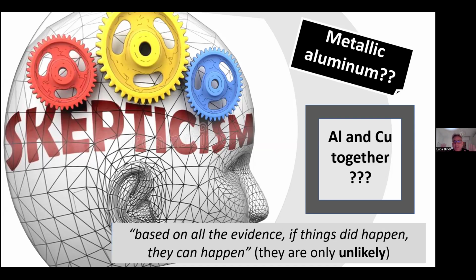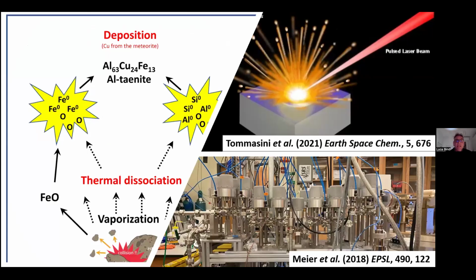But I would say that thanks to these skeptical people, we pushed harder and harder, and we got an incredible amount of data able to help decipher this mechanism. At the beginning, we thought that we could have something like an impact collision, and then vaporization, and the oxides could be thermally dissociated to the metallic elements, and then these metallic elements could form quasi-crystals or aluminum-bearing iron-nickel alloys, and then we would have something like a deposition on a copper-bearing meteorite. This was the idea at the beginning.